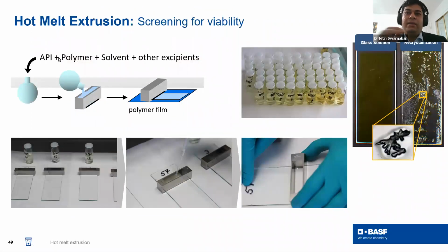Now this is very important for our students, because we don't have this instrument available in our lab. How can we do those kinds of experiments and establish the conditions more suitable for HME? So this is for those students who want to work in the lab. What we need is a simple thing like API. You take polymer, you take solvent, you dissolve it, and this we call the film casting method. You run it over a glass plate, and you can add it with a pipette also, and then you run it over to create one film which is less than 120 micron.